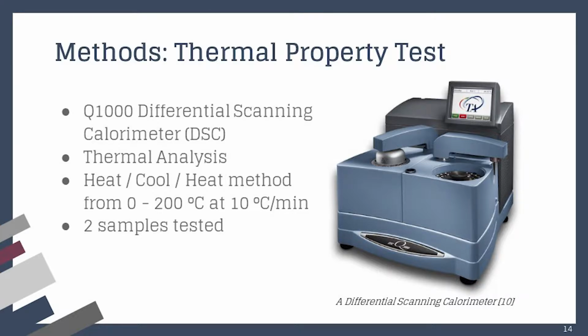The next test we did was a thermal property test, and we used the Q1000 differential scanning calorimeter, or DSC. It was a thermal analysis that measured temperature and heat flow, and the method we used was the heat-cool-heat method, which means that the sample started at 0 degrees Celsius and was heated up to 200 degrees Celsius, then back to 0, and then again for reheating back to 200 degrees Celsius. This was run at a rate of 10 degrees Celsius per minute, and we tested 2 samples per composite.